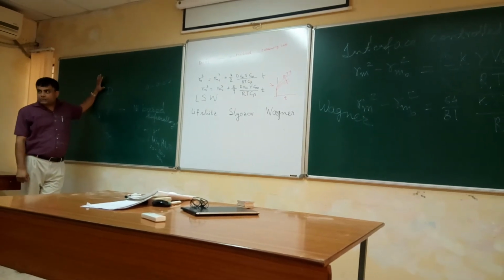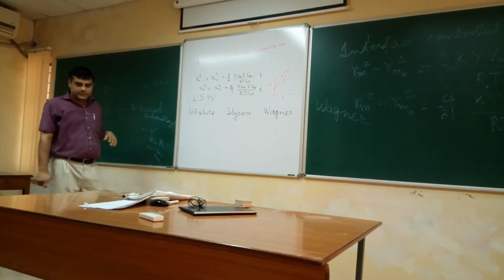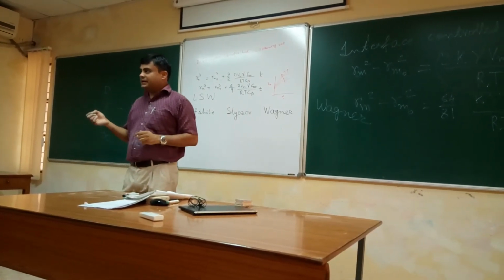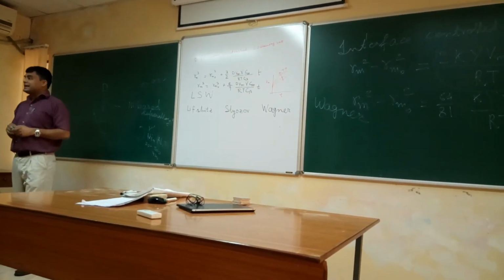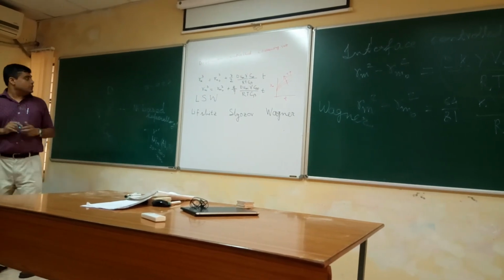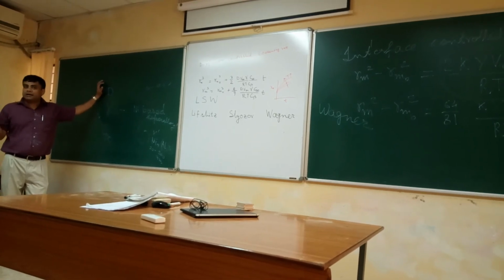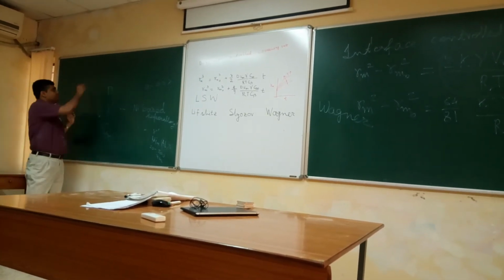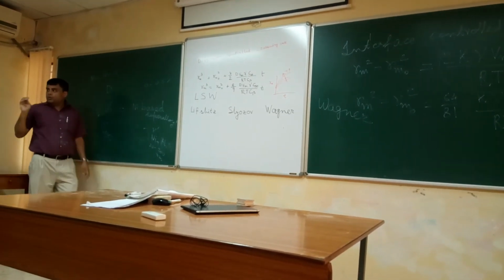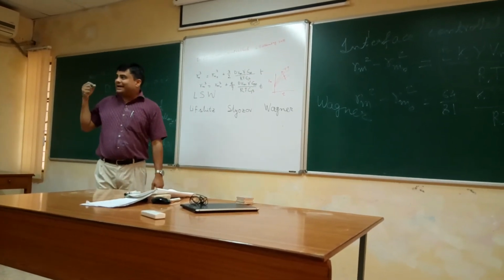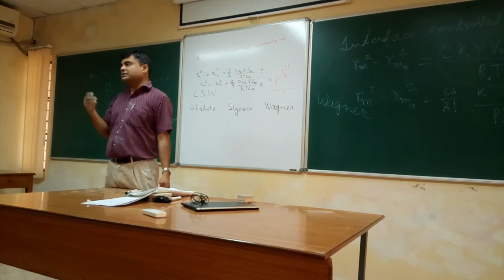You should also use certain alloying in certain cases, for example steel. If you have just cementite particles in ferrite matrix, those cementite particles coarsen faster. So what they use is certain other stronger carbide formers like molybdenum, tungsten, chromium, but their diffusivity, moly diffusivity or chromium diffusivity through the matrix, is much lower.